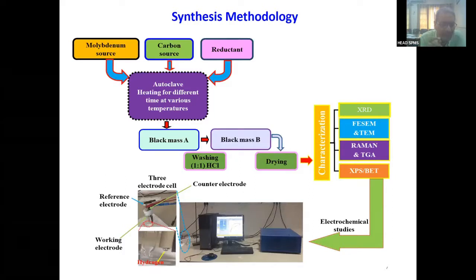So in this autoclave, we put a molybdenum source. It may be any type, like molybdenum oxide or whatever is readily available, and then a carbon source. And apart from this, we also put one reducing element, which is important. Let me tell you that we have worked on different reducing elements, and after a lot of work, we concluded that magnesium flakes, not powders, are a very good reducing element. And the question arises why we are using a reducing element. The reason is different. Whenever we put all these materials in the autoclave, there is some inherent oxygen left inside the chamber of the autoclave.